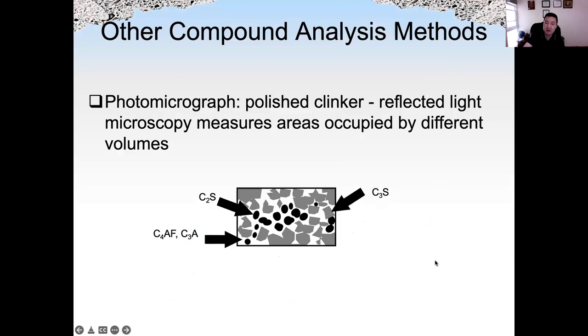So besides the bulk calculation, which estimates the compound percentage from oxide percentage using XRF, we can use some other methods, such as this. This is called a photomicrograph. We get a picture of clinker. We polish the surface of the clinker, take a picture of that, and by counting the areas for each phase, for example, C3S is the angular grid shape like this, and the dark color round shape is C2S, and anything in between C3S and C2S is the mixture of C4AF and C3A. So by measuring the areas of different phases in the picture of the clinker, we can also estimate the percentage of the compound.